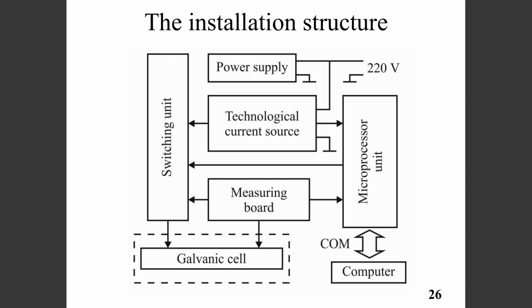The measuring board includes a set of measuring transducers for the following values: current and voltage in the galvanic cell, the impedance of the formed coating, and the temperature of the electrolyte. The measured impedance values allow us to calculate the resistance and capacitance of the coating, which makes it possible to determine the thickness of the oxide layer at a given time. However, since the impedance meter is connected to the same contacts as the technological current source, the microarc oxidation process has to be interrupted periodically, for which a switch unit is used.